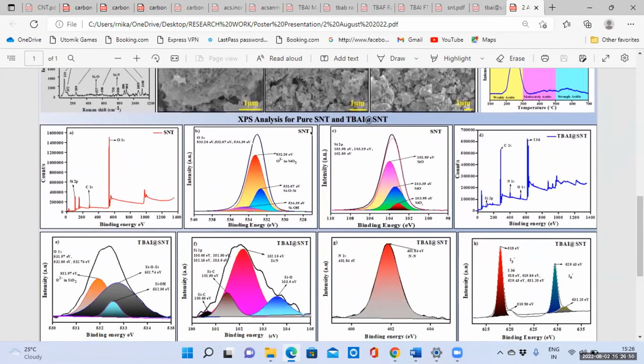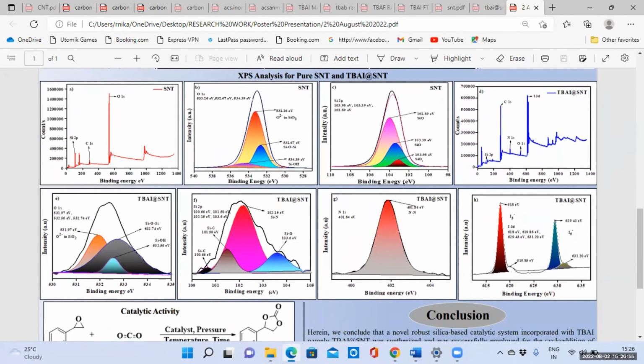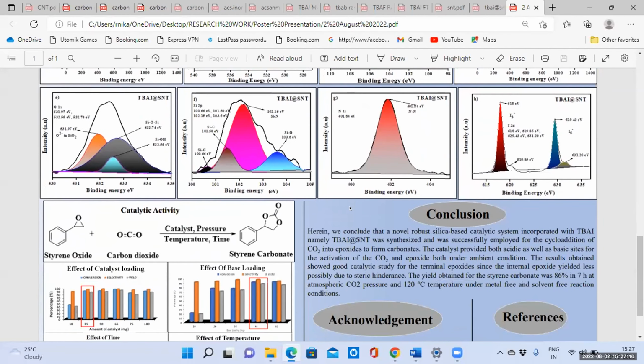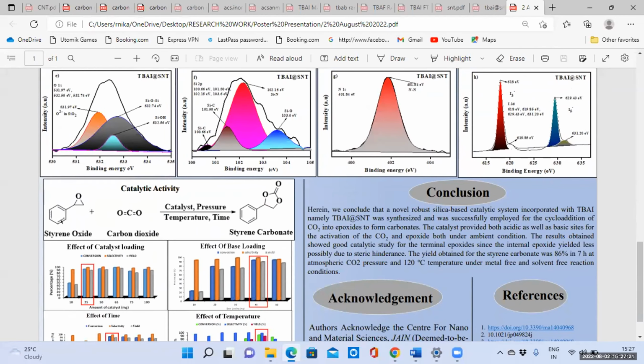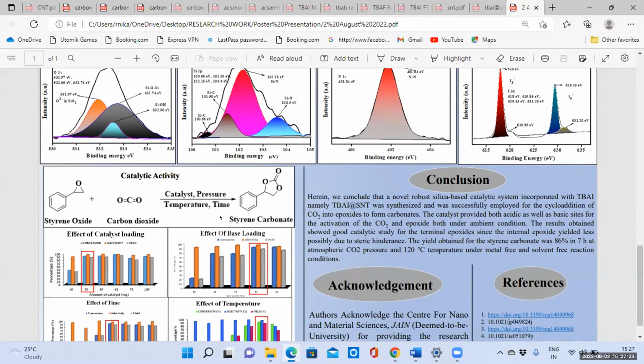Similarly, the XPS analysis was studied to find the chemical bonding for pure SNT as well as TBAI grafted SNT, in which for the TBAI grafted SNT in Si 2p, the deconvolution of Si 2p showed the formation of Si-N chemical bond at 102.15 electron volt, which confirms the grafting of TBAI on pure SNT. After the characterization was completed, the catalytic activity of the synthesized catalyst was studied for fixation of CO2 into styrene oxide and convert it into styrene carbonate.